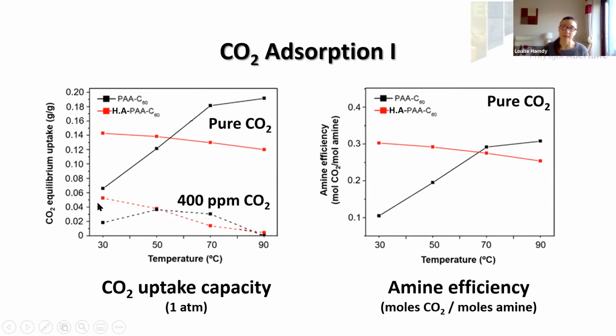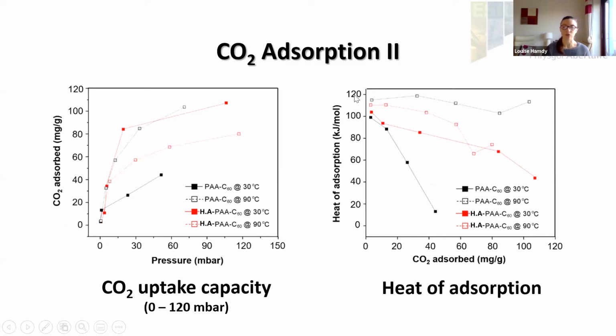But for the hydrophobic additive material, adsorption, as expected from the pure adsorption, is highest at 30 degrees. And this adsorption of 0.053 grams per gram equals about 1.2 millimoles CO2 per gram. And this is on a par with many supported polyamine-based materials. So here we see the adsorption measured at 30 degrees and at 90 degrees for both materials under different pressures from 0 to about 120 millibar. And as expected, we see higher adsorption at 30 degrees for our polyamine material and lower adsorption at 30 degrees for our PAAC60 material, and the opposite at 90 degrees.